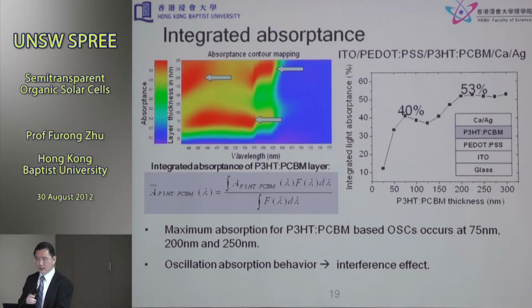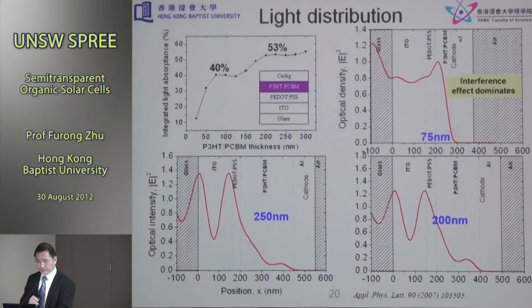Experimentally, you can fabricate a set of devices with selected layer thicknesses in this region. We can look into a little more detail at why my 75 nanometer thick device absorbs more light than the device that is 100 nanometer thick. That's because this is a thin film system, so it works with interference effects. For incoming light, if you can adjust the thickness right, then you have a maximum absorption peak located in the blend layer. That's the reason.